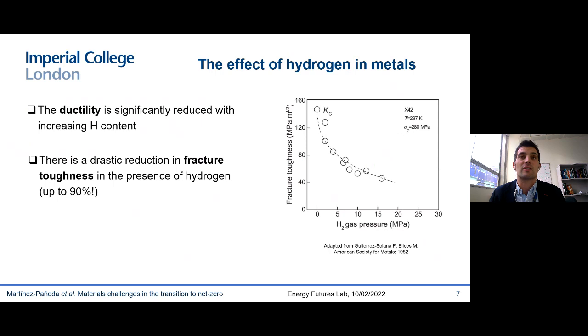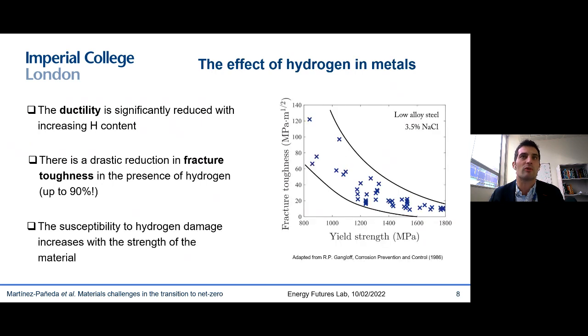Another important effect is the reduction in fracture resistance that we see in the presence of hydrogen. You can see here that an alloy that fails at a fracture toughness of 150 megapascals square root meter will fail well below 40 megapascals square root meter as you increase the hydrogen content. And this is a low strength steel, but in high strength alloys, the reduction in fracture resistance can be of up to 90%. And I think this is a key point to emphasize.